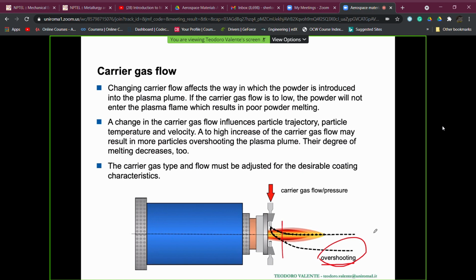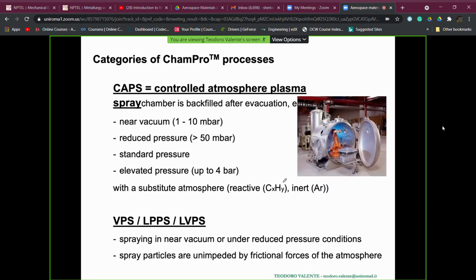And so also this parameter must be set, and is set typically by pre-experimental tests, depending on the substrate to be coated and on the material which is fed here as powder, in terms of composition, in terms of average size.